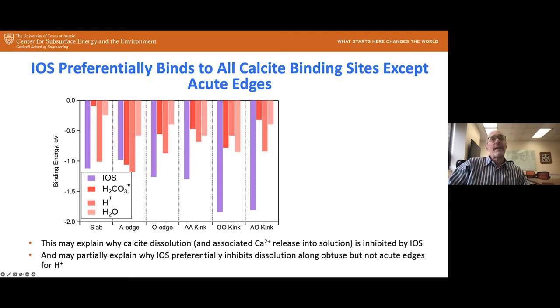In every site except for the acute edge, you see that the binding energy of the IOS is greater than the carbonic acid, the water, or the proton. And so what that implies is that we're going to inhibit dissolution because that IOS is going to bind so strongly, or more strongly, than the molecule that's promoting the dissolution.